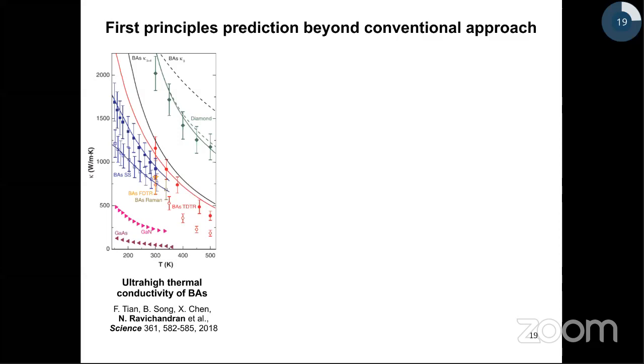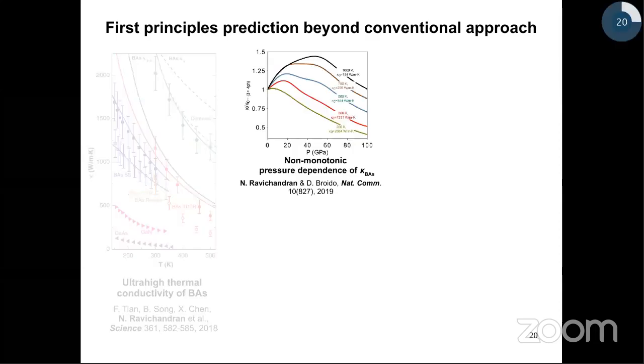So over the past 2 years, I have been developing a unified first principles framework, which includes higher order terms in the free energy and higher order interactions among phonons, to answer this precise question: is conventional theory sufficient for all materials? In fact, using this unified first principles approach extended beyond the conventional theory, I have worked on several interesting problems, such as predicting the ultra-high thermal conductivity of this new material boron arsenide, and as a consequence, a very